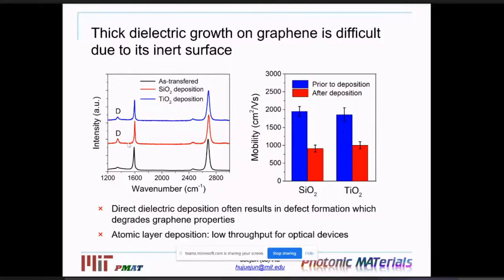If you now measure the transport property of the graphene after deposition, you also see a severe degradation of the mobility. Again, this comes from the fact that this deposition process usually involves elevated temperatures and hence significant damage to the underlying graphene substrate. Now, one way to solve that, of course, is using atomic layer deposition, but the challenge there is that the throughput is very low, so you cannot deposit optically thick films for photonic integration.